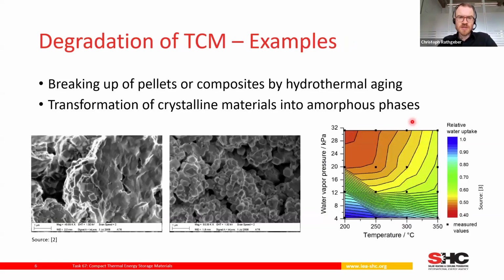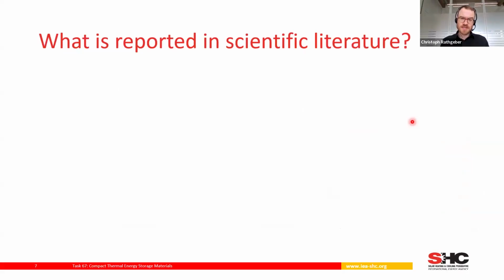And here are some examples for the degradation of TCM. We already heard a lot about zeolite. Zeolite is typically used in pellets, in beads, or composites. During hydrothermal cycling, so at elevated temperatures and humidities, you can observe a breaking up of these pellets or composites, which is, of course, unwanted. You can also observe a transformation of materials that were crystalline at the beginning into an amorphous phase, again leading to a change in the water uptake or a change of the reactivity of the material, thereby reducing the energy density. So that's for the examples to start.